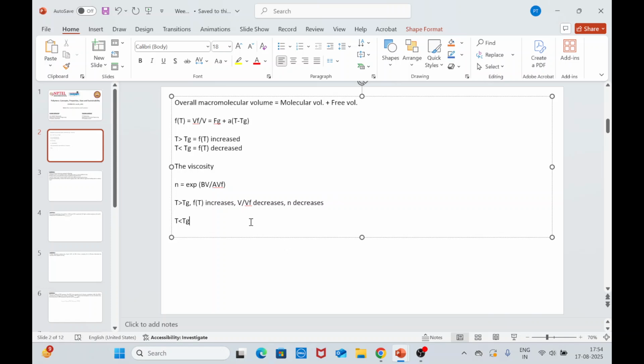Okay, so similarly here I write it this way. F of T decreases, which means V by Vf is going to increase. Exponential of an increasing value will increase, so eta increases, which means viscosity is increasing. So what does this mean? T is greater than Tg, eta decreases, and T is less than Tg, eta increases. So what actually happens at this glass transition temperature point?